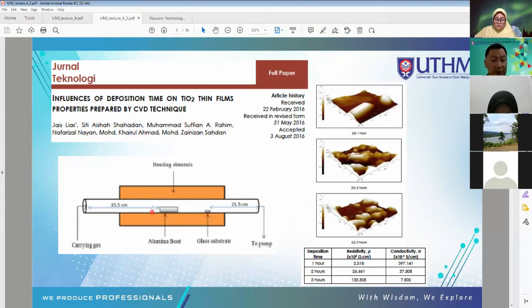It's a much cheaper way. We have an alumina boat and a glass substrate, and this is a ceramic tube. I think it's a big one. We have a carrier gas on one side and the pumping on the other side, and then we put it inside the oven, so that inside this alumina boat we put a powder. That powder will evaporate and then deposit on this glass substrate, a very thin one. After we do the process, 1 hour, 2 hours, 3 hours for example, we can characterize the thin film that we grow on the glass substrate. This is an example of titanium dioxide, created by my colleagues, Dr. Zainizan and Dr. Khairul. This is an example of a simple CVD process that we can have in our lab.